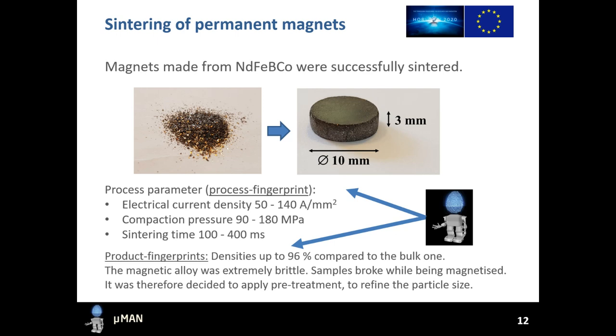Permanent magnets made of neodymium, iron, boron, and cobalt were sintered as well. The alloy resulted quite fragile and therefore rings were not sintered without being broken. This happens because the more dramatic thermal gradients between sample and tools did not make possible to have a good densification and therefore high mechanical strength.